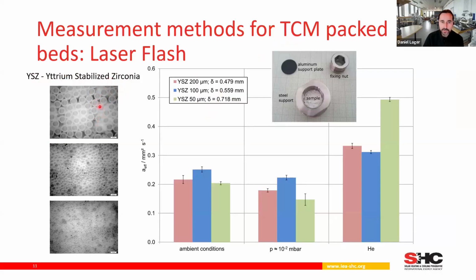But we measured here the thermal diffusivity with different gases. And you see here at ambient conditions, the thermal diffusivity is higher than when I measure under vacuum conditions. So in that case, it really depends on the gas phase between the particles. When you look at this graph on the right side, you see the influence of helium in the same measurement. So we did not change the sample, we just changed the gas phase. So the so-called effective thermal conductivity strongly depends on the gas phase you have in your system.